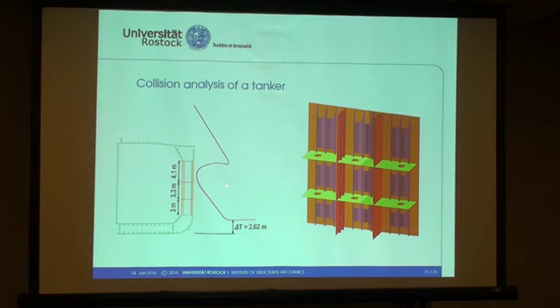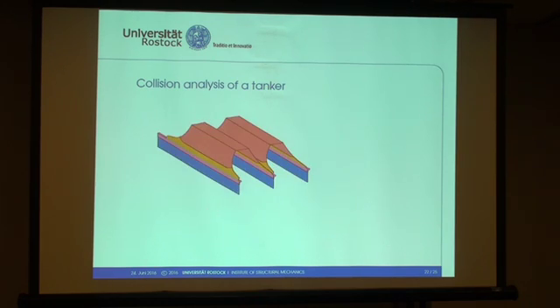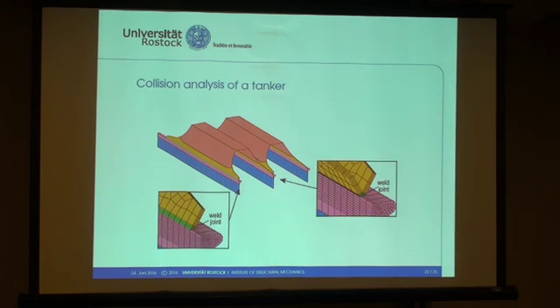Here is the cross-section of the finite element model I just showed, and in the orange area you can see the inside of the outer shell, the frames and the stringer decks in green, and also the bulb profiles and the PVPS on top of them. To investigate the load capacity of these weld joints between bulb profile and PVPS, I discretized that area with relatively fine solid elements. You can see here the solid elements of the PVPS, the weld joint, and the bulb profiles, and I applied the calibrated Rice and Tracy failure criterion to these weld joints.